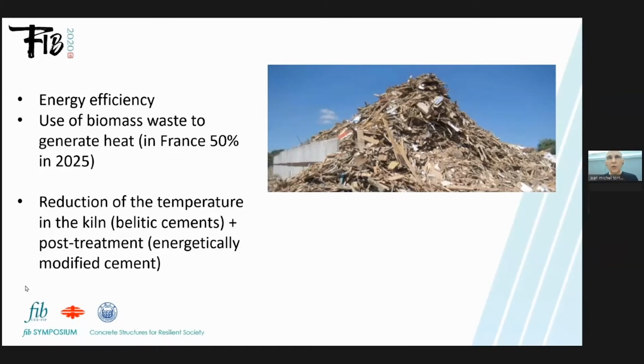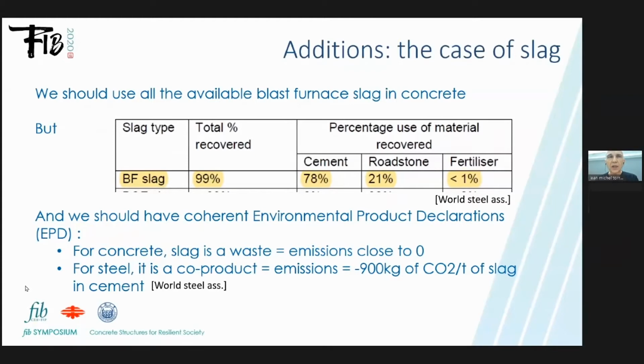Of course, we know that we can use additions, but with additions we have some limitations. Here I present the case of slag. Of course, we should use all the available blast furnace slag in concrete, but you can see that almost 100% of the blast furnace slag is recovered, and almost 80% is already used in cement. So we can just divert 21% from road to concrete, but that's not a very large quantity. And the second point is that we should have coherent environmental product declarations, because for concrete, slag is a waste.